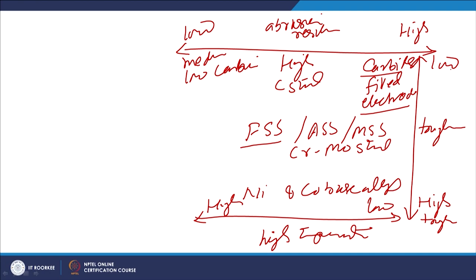The medium toughness and medium abrasion resistance is available with the low and medium carbon steels, and good toughness is available with the ferritic, austenitic and martensitic and chromium molybdenum steels, while on the other hand on the top we have abrasion wear resistance. So all these like high carbon steels, carbide filled electrodes. So this is a broad guideline for choosing the materials for various applications.